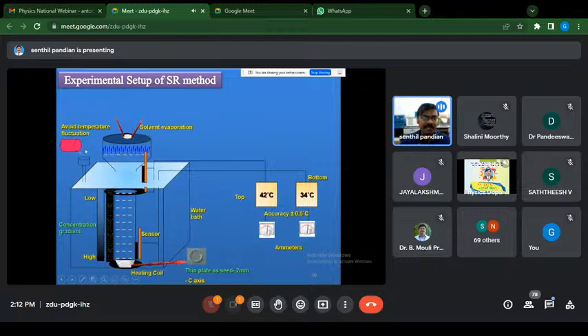And to avoid the temperature fluctuation of the daily variation, water is frequently added inside this water bath. So we have to maintain this level to maintain the uniform temperature. Freshly prepared saturated solution is also frequently added inside this SR glass sample in order to avoid fungus formation in the grown crystal. After a few weeks or few months, depending upon the solubility of the material and the temperature you have selected for this material, the crystal will be grown like this. So this is the diglycine barium chloride single crystal grown by this SR method.